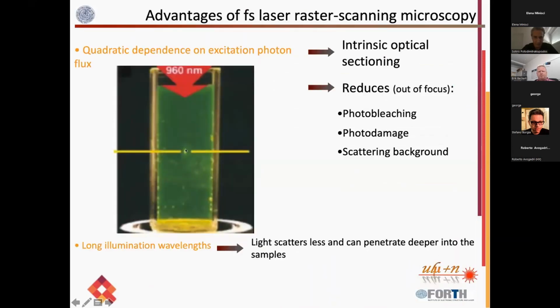Here is what happens when we use this femtosecond laser. Here is fluorescein, a liquid, and you can see here the surface of this medium, and the light spot is this one here. So actually we are below the surface, and this spot is what is raster scanned below the surface of the sample. Of course, by moving the objective up and down, we can move this spot up or down and have very nice axial resolution. We can choose a layer, a surface layer, a layer inside the sample that we want to examine for defects.